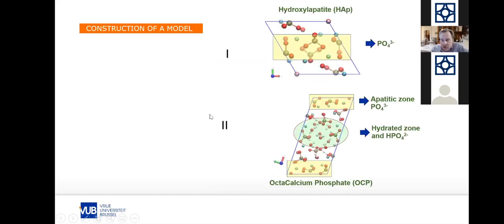And then there is a question. I go very fast. It's because in hydroxyapatite, we only have this type of phosphate, pure PO4. We don't have the HPO4, but there is a polymorph in nature that exists, and this is octacalcium phosphate. There you have a structure which contains a part that looks like apatite, so hydroxyapatite, and we have a zone where we have the hydrogen phosphate. So this can be an ideal start structure for our simulations.